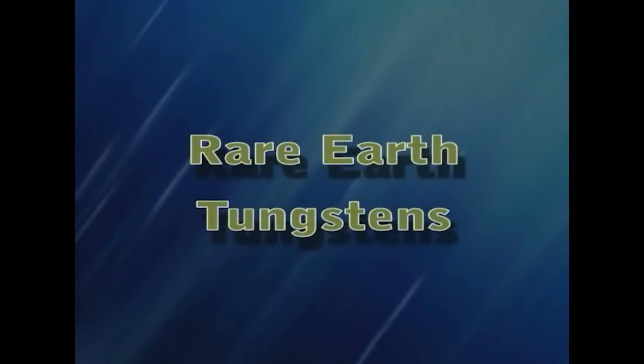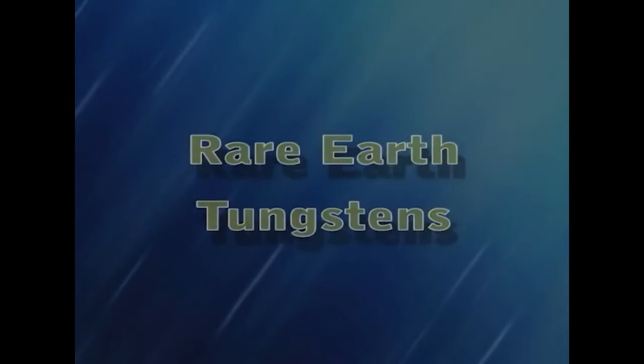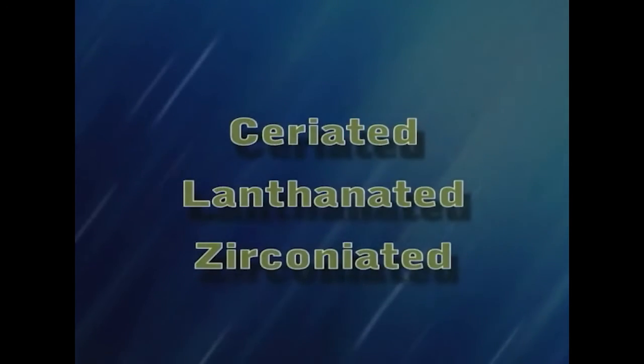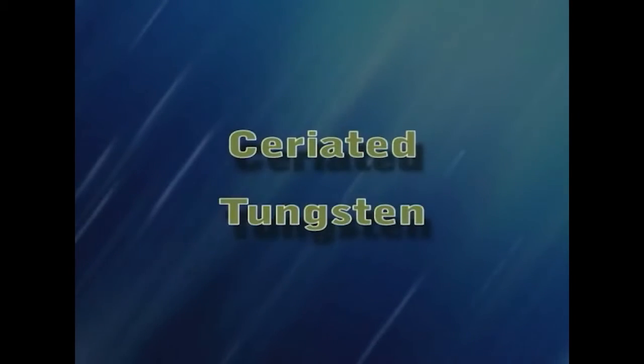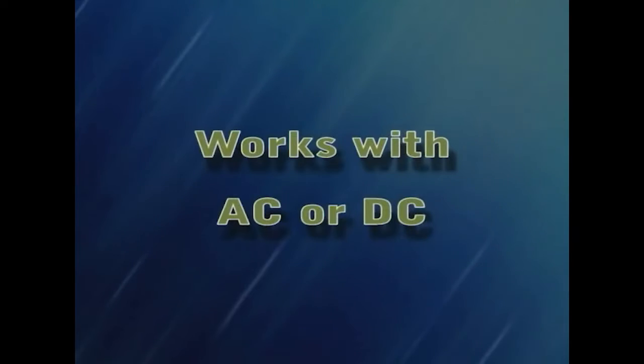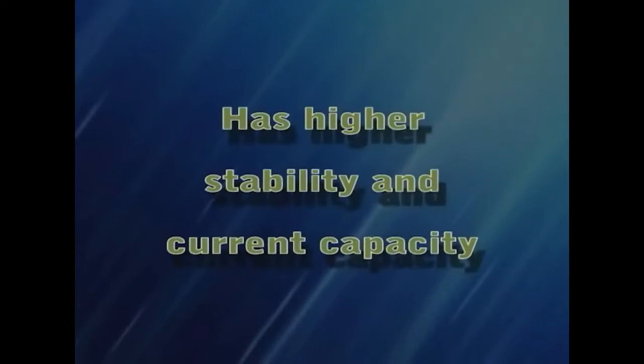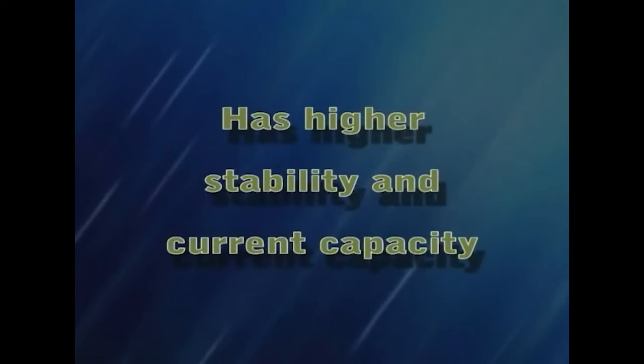Modern welding machines can make better use of the new rare earth tungstens, ceriated, lanthanated, and zirconiated, none of which have any radioactivity at all. Ceriated tungsten can be used for both AC and DC welding, and it has better arc stability and better current carrying capacity than thoriated electrodes. Ceriated electrodes are color-coded orange. It's a good general-purpose electrode, and these are one of my favorites.